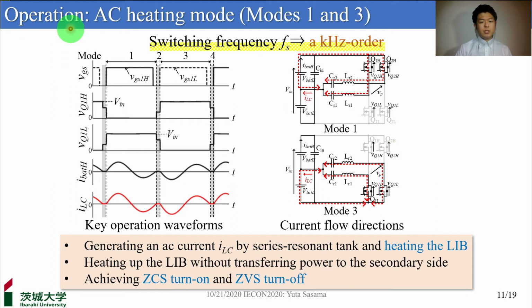This slide shows the operation of AC heating mode. In this mode, switching frequency is a kilohertz order to heat the battery without the charge-discharge reaction. Only primary side switches are given signals and generate the AC current ILC by series resonant tanks. It should be noted that high side switches synchronize, and so do low side switches.